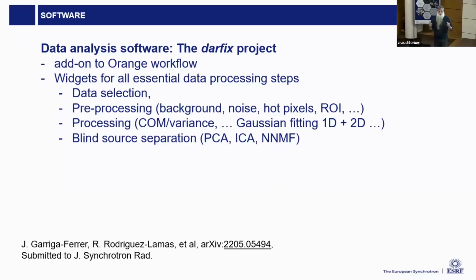And then the actual processing, which is specific to dark field microscopy, which is making maps of the center of mass, of the peak position, of the variance, Gaussian fitting in 1 or 2 dimensions. And we have implemented also some first machine learning algorithms like principal component analysis, independent component analysis, and non-negative matrix factorization, which will allow us to automatically identify, for example, domains in a ferroelectric without having to visually inspect these images. The article for this is under review, and I hope that it will be published very soon.